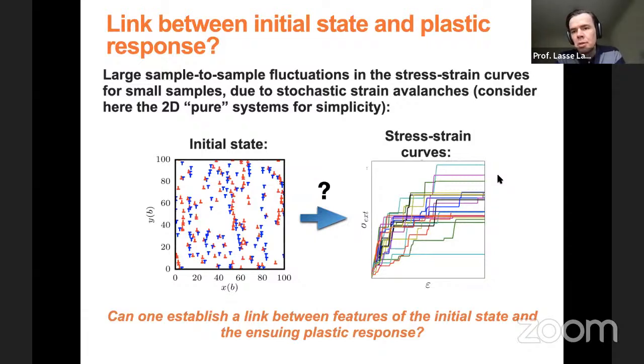And then you can repeat this procedure. So you generate another random initial dislocation configuration, let it relax, you get another state that looks a little bit different from this one, and then you get a different stress strain curve. So you have these sample fluctuations that actually are pretty large in small systems. So now the question is, what exactly is the link between the initial state here and the stress strain curve that you get when you apply stresses? So can you somehow establish some link between some features of this initial state and the stress strain curve?